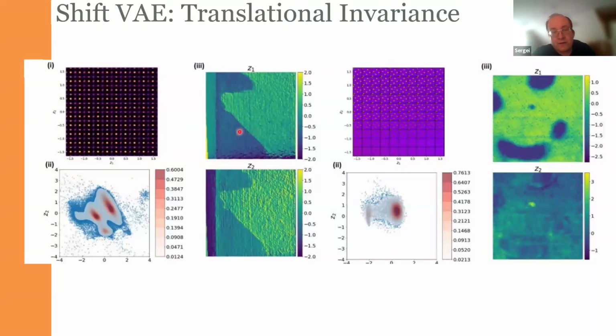If we run the translational VAE on it, you can see that there are clearly seen regions with a different latent variable. So these regions are ferroelectric domains. And we got that without finding atoms. We simply used the translational invariant autoencoder, and it was able to separate the ferroelectric domains. And of course, it separated the substrate. And the latent distribution basically corresponds to one ferroelectric domain phase, another ferroelectric domain phase, and the substrate phase.